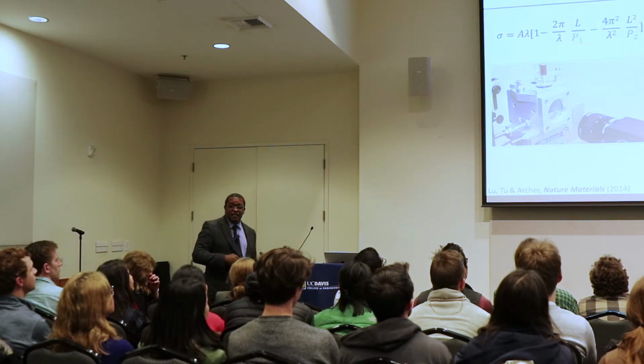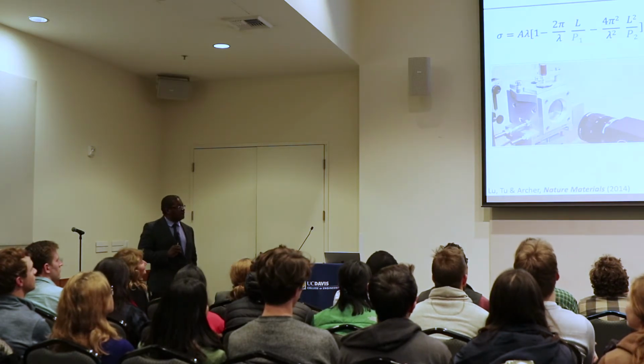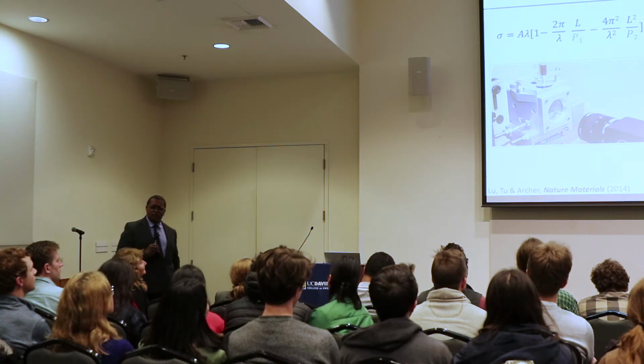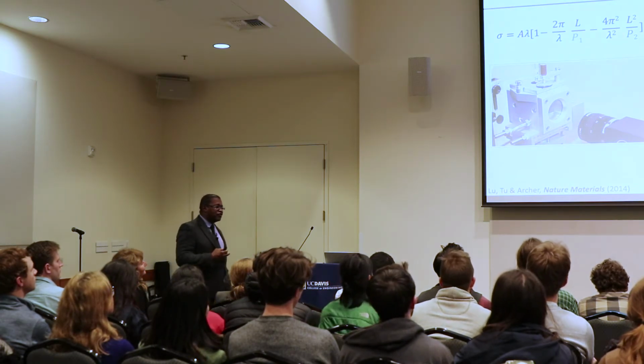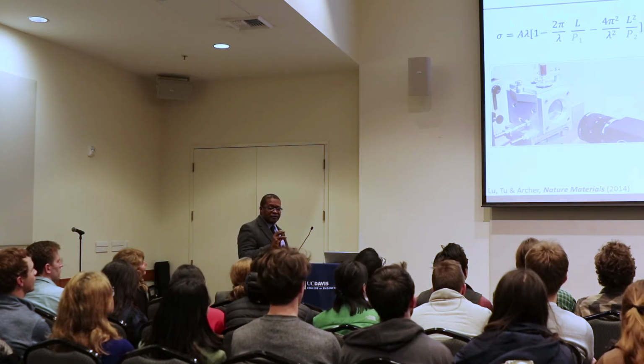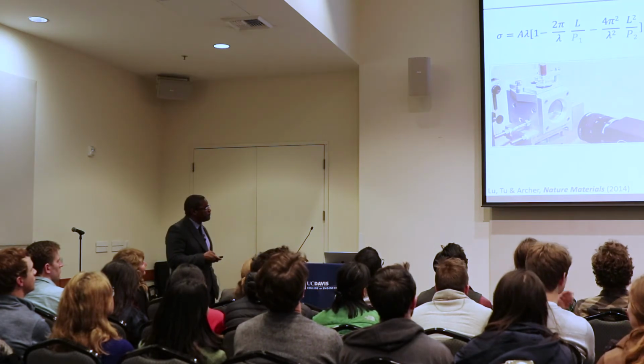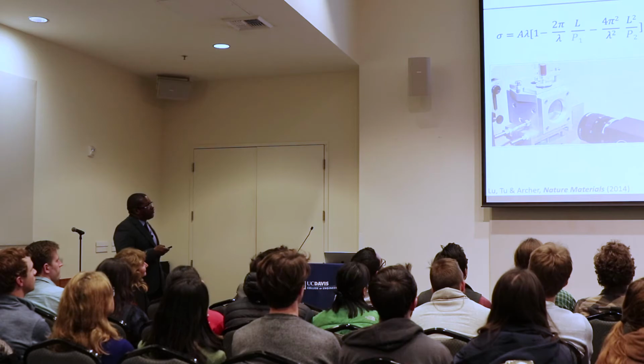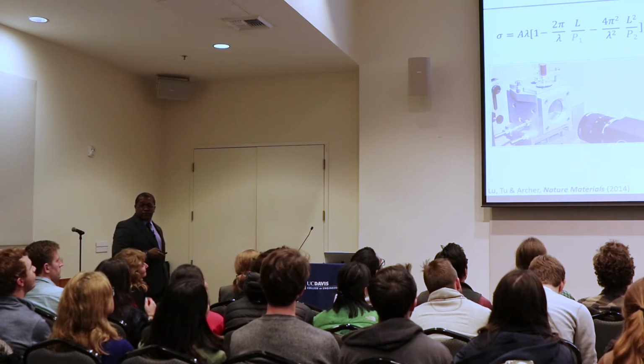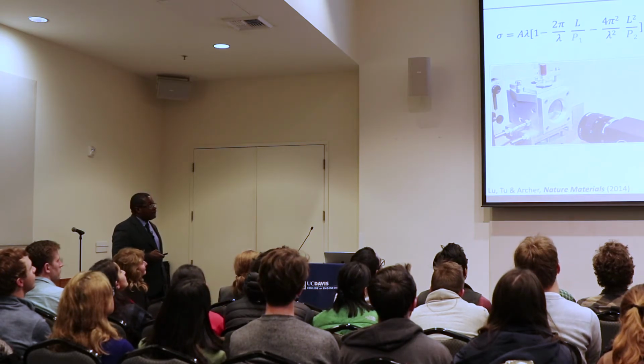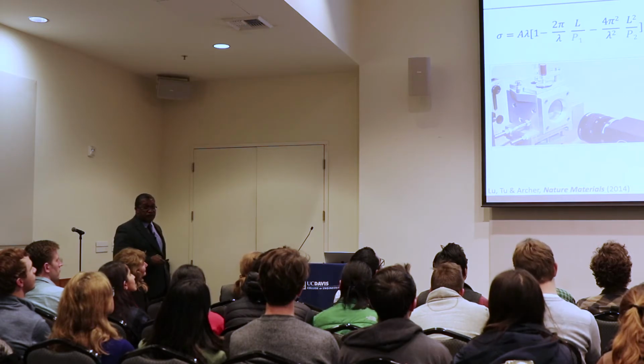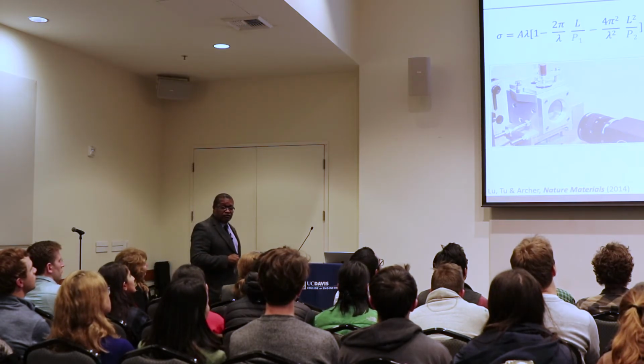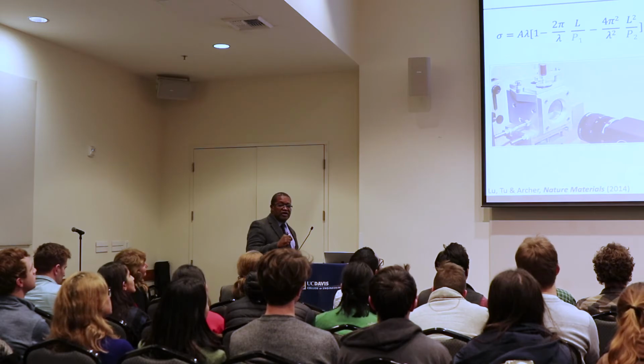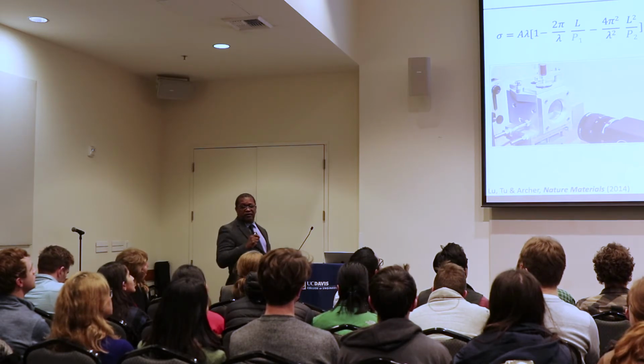Okay, good. So this is all going great up to now, but I wanted to know more. So we have these two dimensionless groups, and I haven't told you anything about them other than their effect on this critical pore size. So what we decided to do is play with one of them, this group P2, because P2 is the reciprocal of the surface tension, something we thought we could change easily by adjusting the chemistry of the electrolyte.